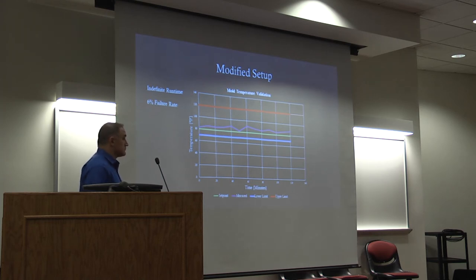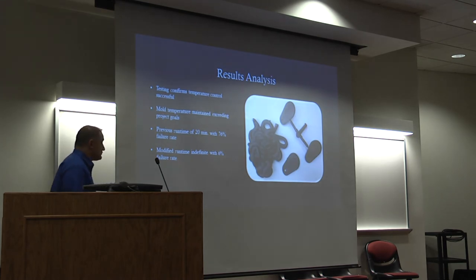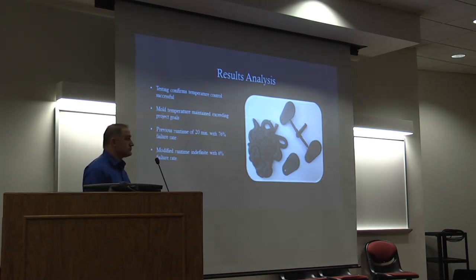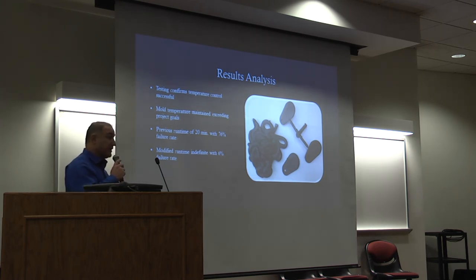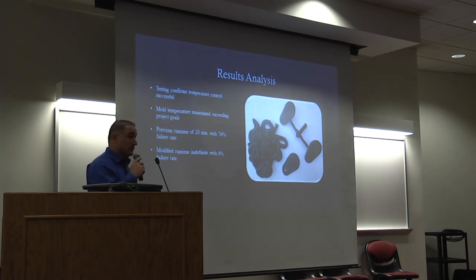Another big point of that was we took it from a 76% failure rate down to a 6%, so that's a drastic increase in efficiency. And all those deformations that we had in the second run when it was temperature controlled were at the very start of the cycle. We believe that with our changes being made and the failures coming just at the beginning of the cycle when the mold is really at its coldest point, once you do your initial setup and preheat and pre-stages of running of the parts, those will even be eliminated by having the mold be brought up to temperature before you run your first shot.